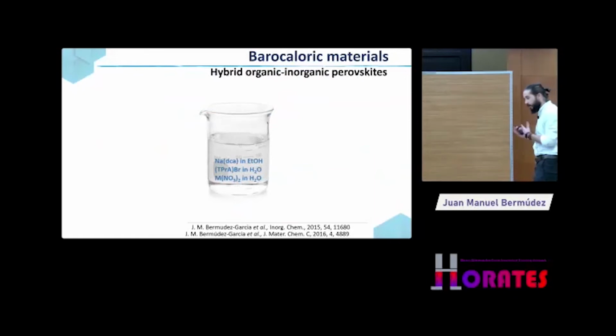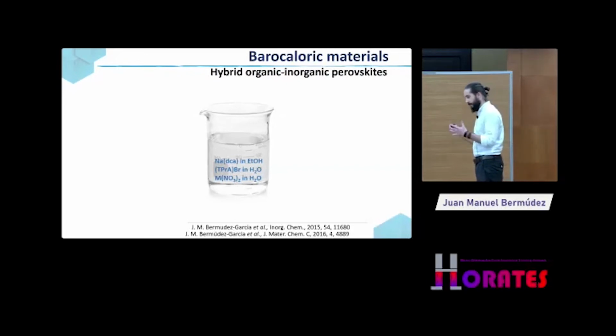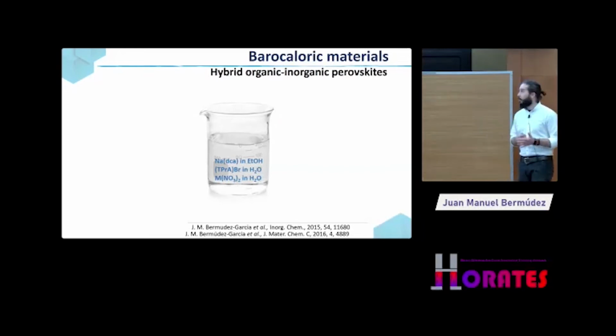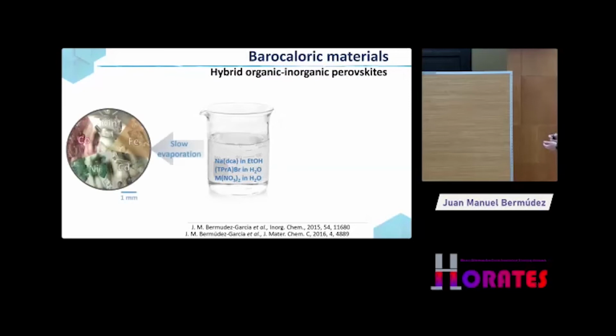If you want to implement a material into the market, the first thing that you need to think about is: is this synthesis eco-friendly, cheap, fast, scalable? Well, in the case of our materials, this synthesis fulfilled all the requirements because it was quite simple. We were using an aqueous solution with a bit of ethanol with the different chemicals. And then if we did a slow evaporation, we were able to obtain different materials by using different B transition cations of manganese, iron, cadmium, nickel, and cobalt in the form of single crystals.